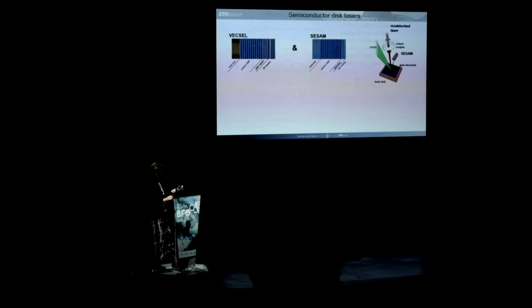As you know, I'm in the business of mode locking. So I invented this SESAM device, which solved the Q-switching problem in ion-doped solid-state lasers, which is a semiconductor saturable absorber on top of a Bragg reflector. Now, this optically pumped thin disk laser, or the VECSEL, is also a semiconductor. It's a bottom high-reflecting mirror, a gain region with multiple quantum wells, and then an anti-reflection coating. When we did the first passive mode locking of these lasers, we used a V-shaped cavity with the SESAM as the saturable absorber and the VECSEL as the gain chip, and successfully mode locked this laser. But then, of course, because both are semiconductors, sometimes it really doesn't want to go.